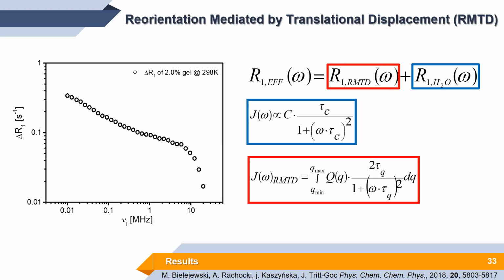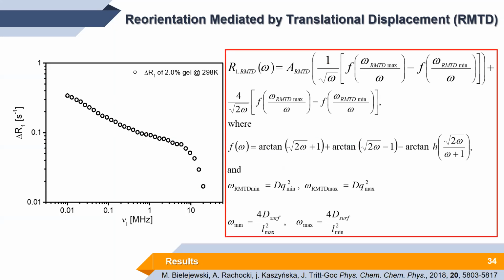One, which can be described with the spectral density function of Lorentzian form, will be for the solvent molecules which do not directly interact with the surface of the gel matrix. And the second contribution, described by the RMTD model, is for the molecules that interact directly with the surface of the gel matrix. So the low frequency range dispersion will be described by RMTD, and the high frequency range dispersion will be described by the BPP with a Lorentzian form of the spectral density function.